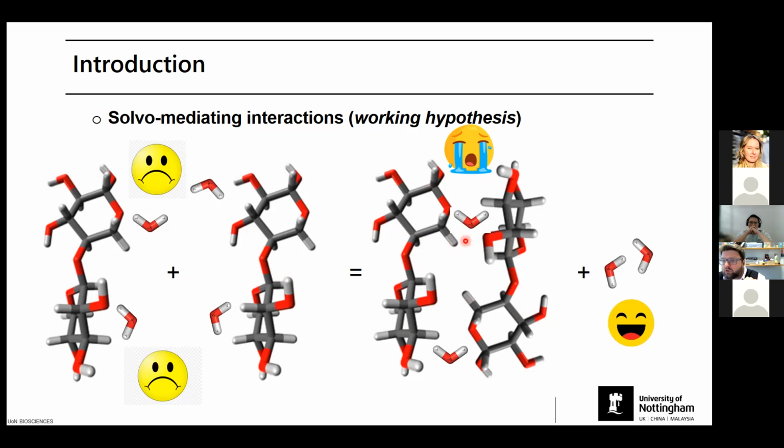So unlike most of the junction zones that go with the expulsion of water, like for example cellulose or starch, when the starch or cellulose molecules interact, usually the water goes altogether. Here, the water is retained in the junction zone. So think about pectin, where it is the ions of calcium that act as a crosslink. Here the water acts as the crosslink. And of course, the number of water molecules in this case are entropically in an absolutely dead state. They are really sort of unhappy entropically.